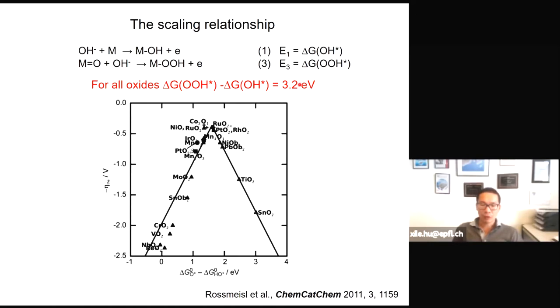minimal overpotential. Because of this scaling relationship, we can now use the energy difference of oxy radical to hydroxy radical, the intermediate step, as the so-called descriptor. So this is the x-axis, and the y-axis is the theoretical thermodynamic overpotential. Because the difference is always 3.2 eV, the best one can do is to have an energy difference of 1.6 eV. So each step takes 1.6 eV, and that will give rise to an overpotential of about 0.35 eV. That's the best one can do. If the oxy adsorption intermediate is easier or more difficult to make, you increase the energy of one of these steps and give rise to a higher thermodynamic overpotential.